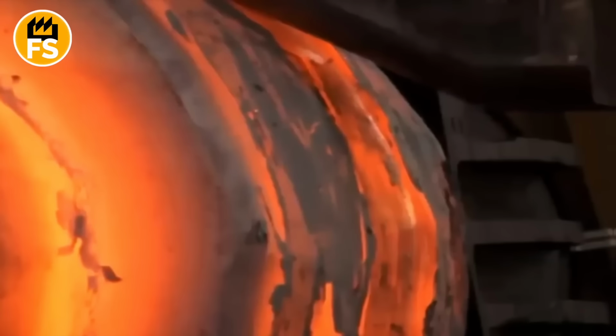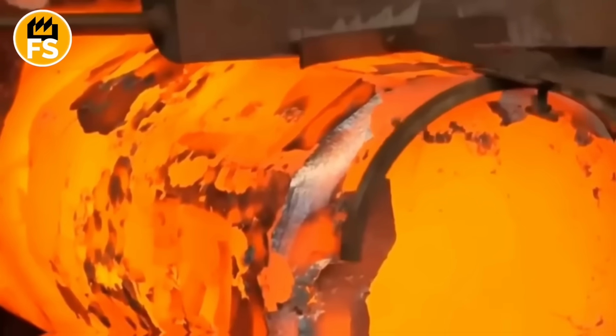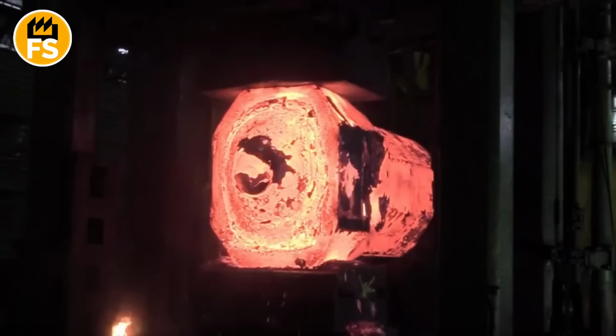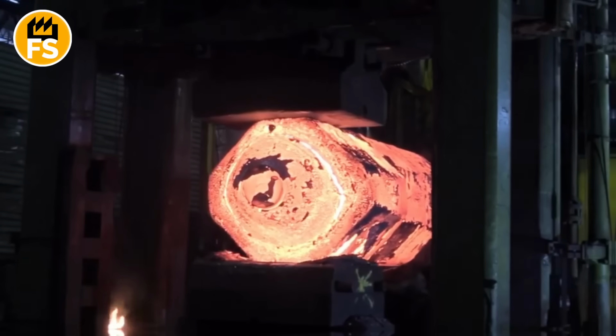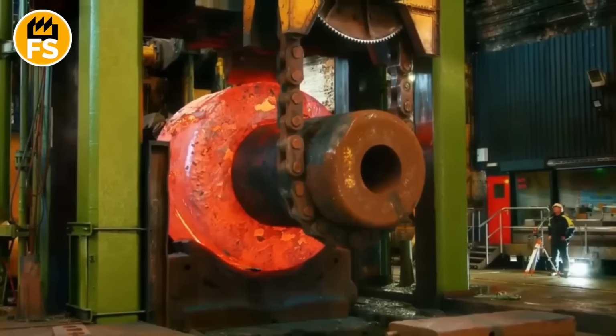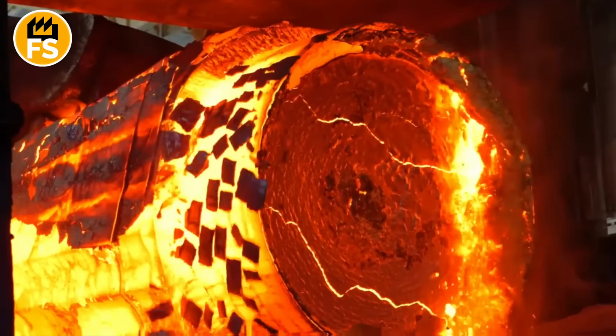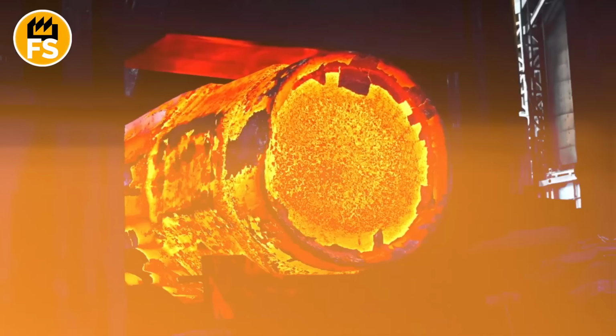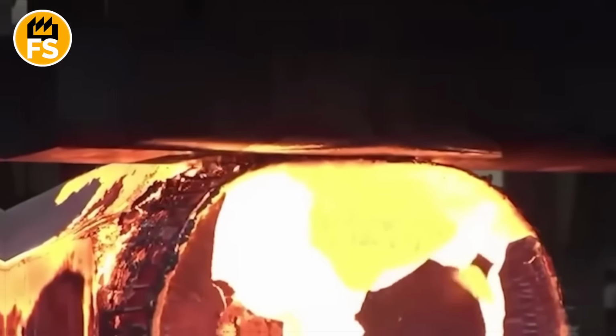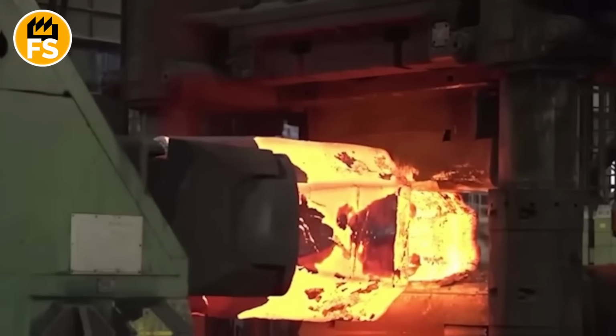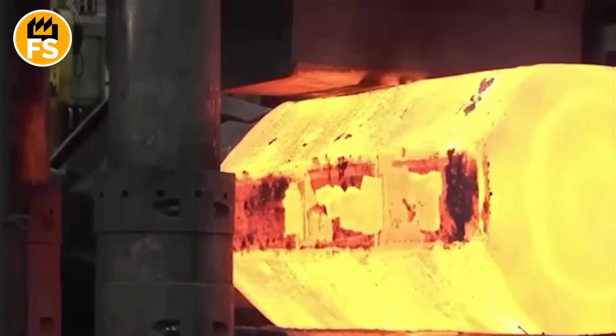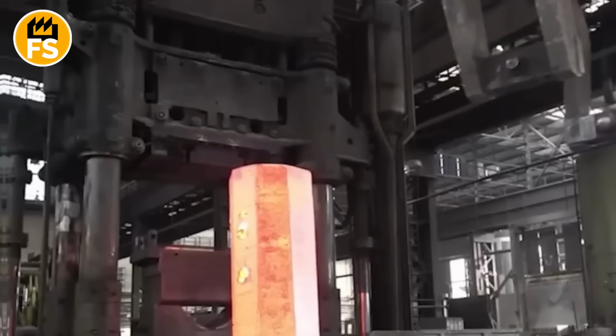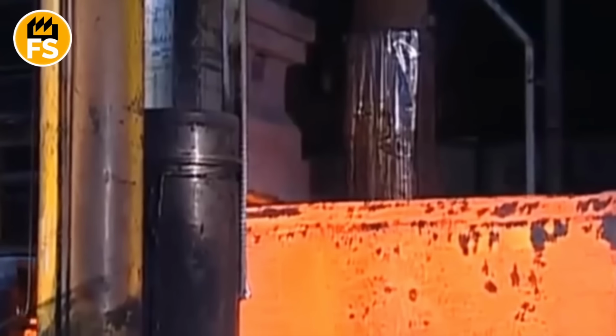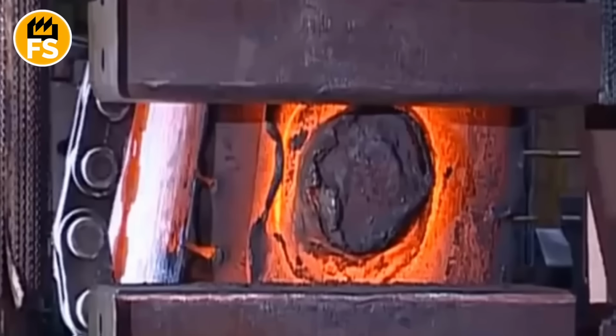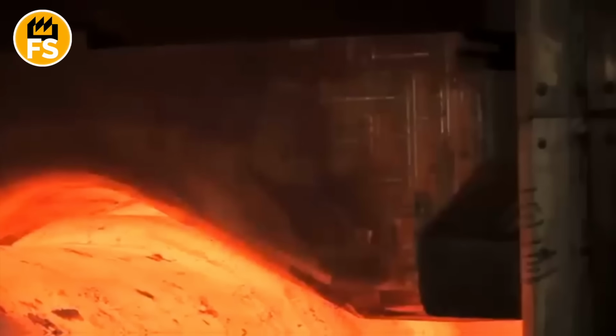The forging itself is done on giant hydraulic presses capable of creating pressure in the tens of thousands of tons. The press breaks down large, brittle cast crystals. The pressure compresses the metal, eliminating microscopic voids that may have formed during casting. The metal gains a directional fibrous structure, which significantly increases its strength, toughness, and fatigue resistance. The forging process for such an ingot takes several months. It's a constant cycle of heating, pressing, rotating, and reheating. Each press stroke is a precise calculation aimed at achieving the required internal geometry and mechanical properties.